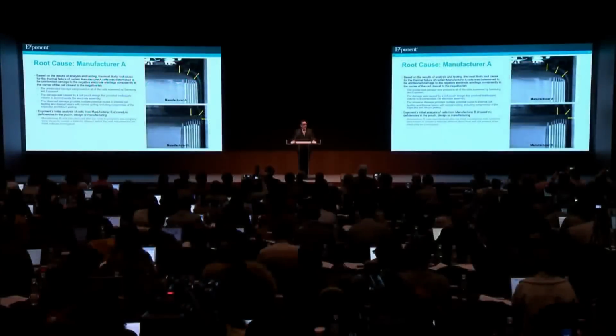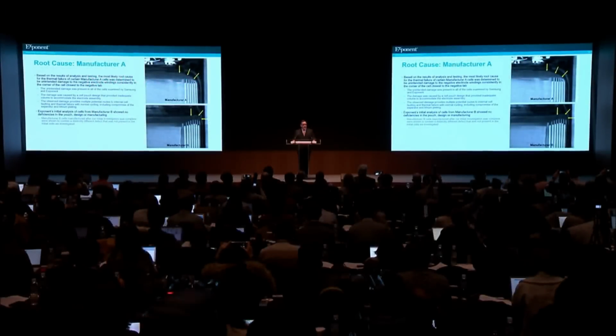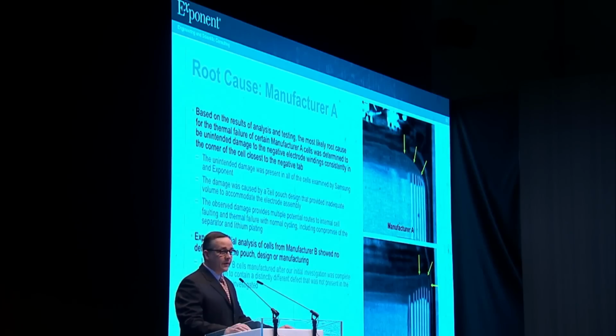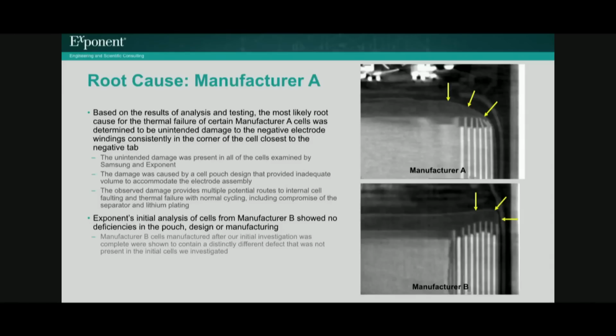Our investigation into root cause for the failure of the cells provided by manufacturer A showed that damage to the outermost windings of the negative electrode closest to the negative tab of the cell was the most likely cause for the thermal failures. This negative electrode damage was present in all of the cells that were examined by Exponent and was found in data that were collected by Samsung and made available to Exponent. Through measurement and observation, it was found that the negative electrodes were damaged because the design of the cell pouch did not provide enough room.